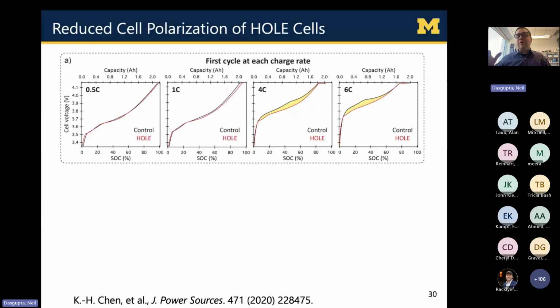Now here is a little bit more into the weeds, so if you're not an electrochemist, that's okay. This might be a little bit beyond what you're interested in. But if you are, if you just look at the voltage versus state of charge curves right here, what we can see is that for the control and the patterned cells, they're essentially the same, which again is a good thing. We don't want to degrade our battery at slow charging rate. But under the fast charging conditions, we see the cell polarization, the excess voltage that is required to charge it at this fast rate, becomes more and more significant at 4C versus 6C charging.